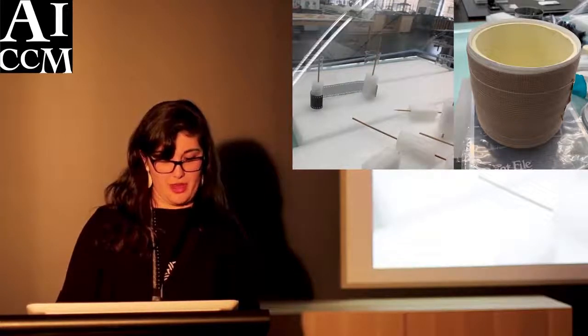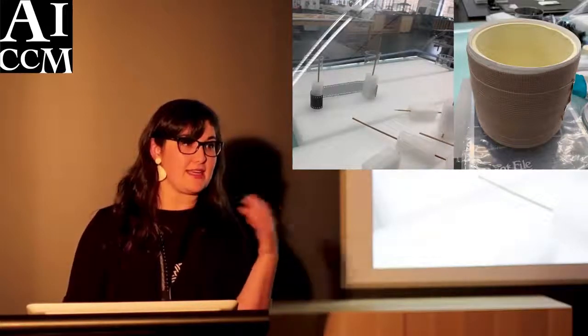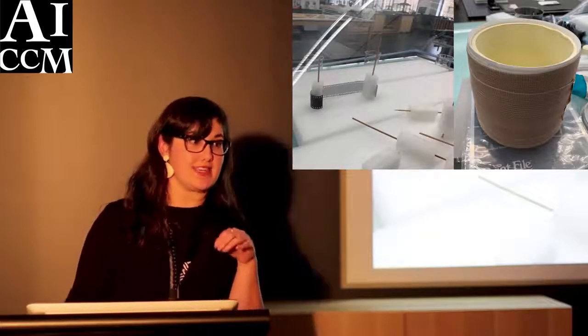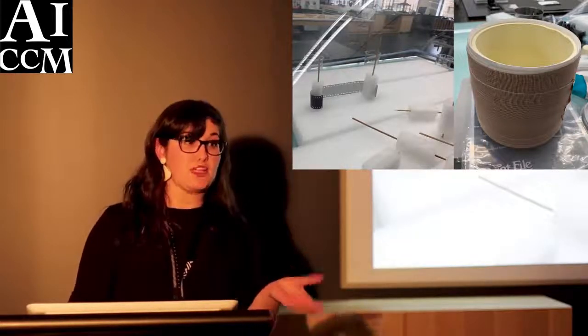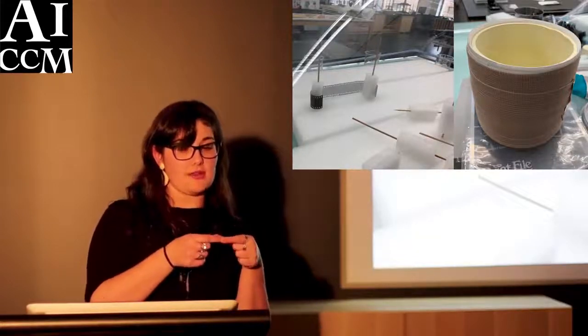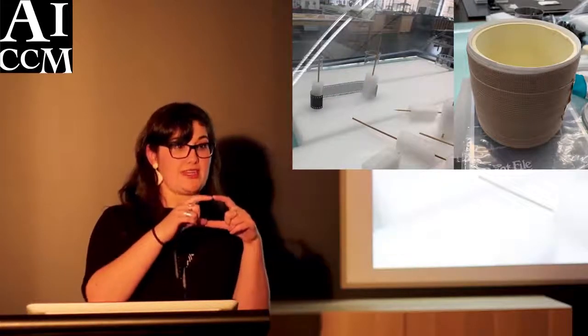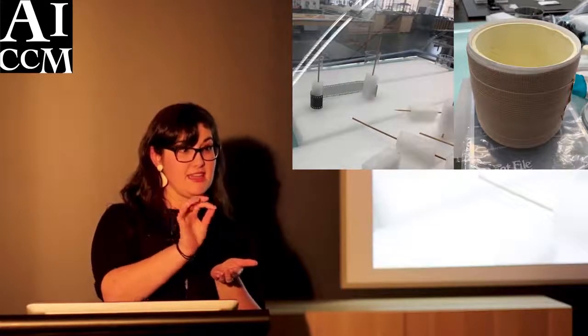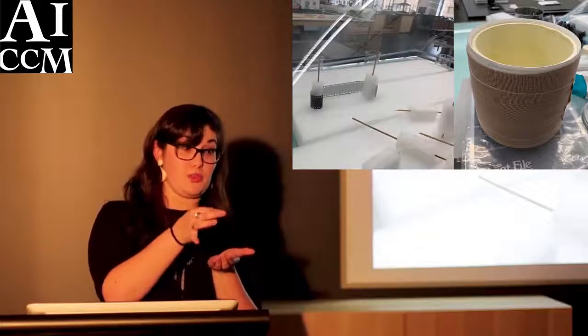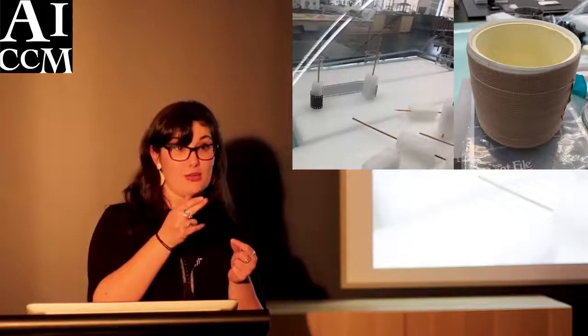Also, she took me through the burn test, which I think most of you know about, to identify acetate and nitrate. They don't usually practice that though. What they do is the diphenylamine spot test, which you can do with 3D nitrate objects or 2D. But she showed me a modified version where you get glass microscope slides, and they have a frosted end which is a bit rough. All you do is you grab the negative and rub the side on that rough bit, and that's enough residue apparently, so if you drop the diphenylamine on that spot, it will give you a positive or negative result, which is a really great alternative to actually cutting off a corner and sampling it.